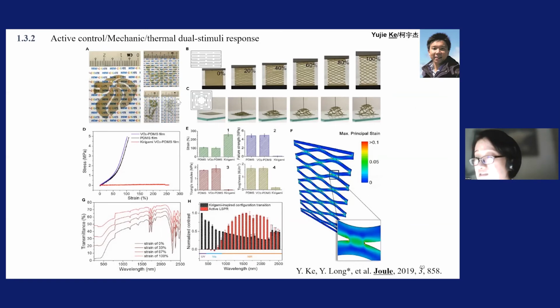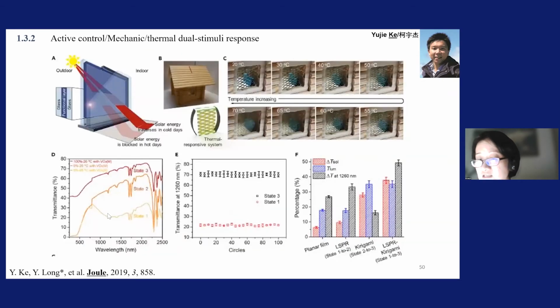So for example, in this case, you can imagine winter more or less like this, summer more or less like this. So we use what we call kirigami structures. You cut in different ways, you can get different patterns. By combining this mechanical way, we can further enhance Tlum and delta Tsol at the same time. You can see we demonstrated, for example, without kirigami, your summer is here, winter is here. But with kirigami, your summer is still here, but your winter has much more enhanced transmission, right?